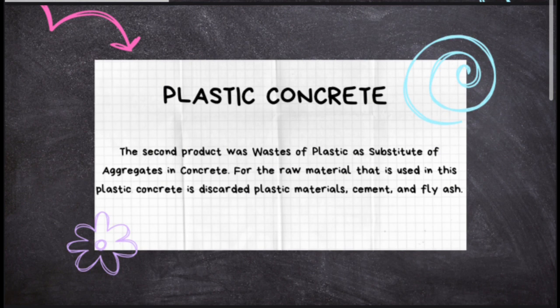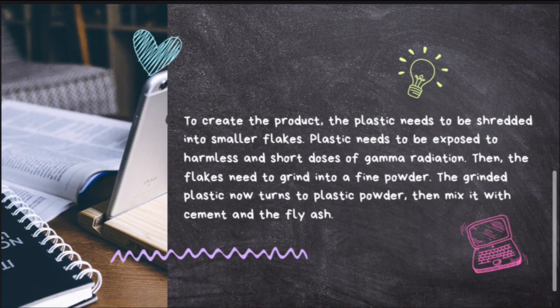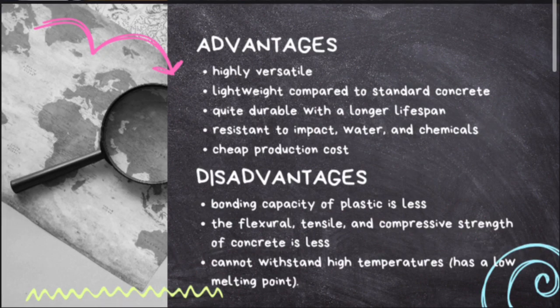The second product of our product is plastic concrete. The second product was waste plastic as a substitute for aggregate in concrete. The raw materials used in this plastic concrete are discarded plastic materials, cement, and fly ash. To create the product, the plastic needs to be shredded into smaller flakes. Plastic needs to be exposed to a harmless and short dose of gamma radiation. Then, the flakes need to be ground into a fine powder. The ground plastic now turns to plastic powder, then mix it with cement and the fly ash.